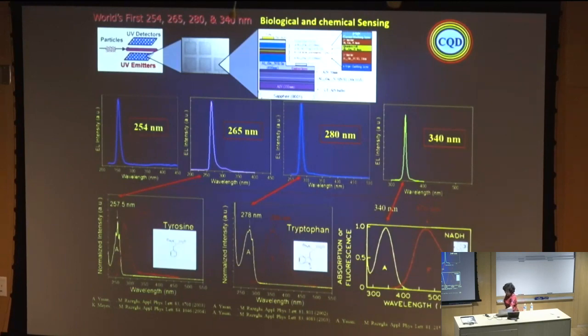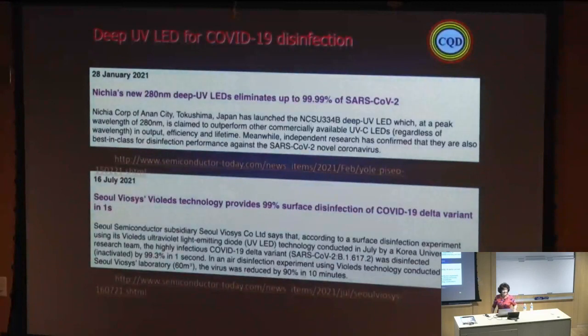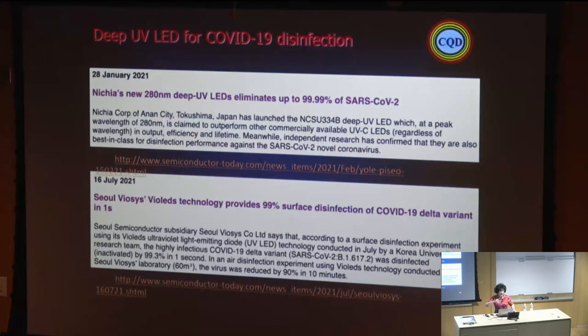At the time, nobody could really believe that it was possible, because of p-doping of the aluminum gallium nitride and this wide bandgap, the large bandgap material. Again, it was my patent a long time ago. But what happens? Look here. Just last year, they demonstrated that this 280 nanometer LED that we developed long time ago, not only for anthrax, can kill coronavirus on surfaces and in the air that we breathe, more than 99%, in less than 1 second. And not only that, by pairing this LED with the detector that I showed you, we can make a small system that rapidly detects biological agents, such as all of the different viruses, according to their fluorescence spectrum.